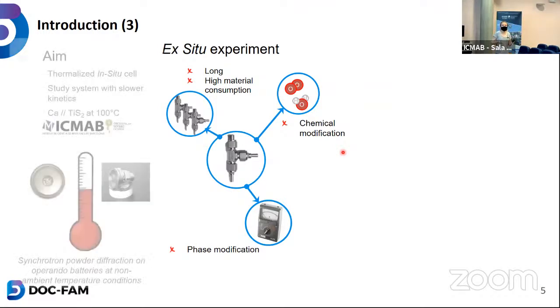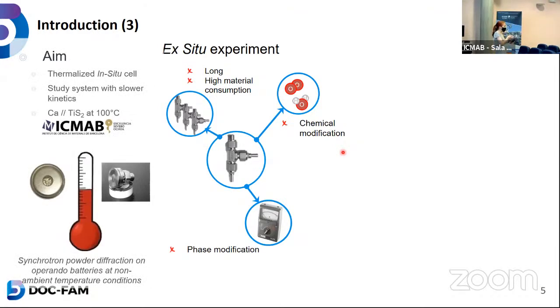So I use an in situ cell that allows you to do the cycling and collect patterns at the same time. So you do not have to handle your material, and you can collect many data with one single cell. However, as I told you, when I started my PhD, the state of the art with calcium was 100 degrees because calcium is a very slow system. So we needed a thermalized in situ cell that did not exist at this time. So my project was to develop this kind of cell.